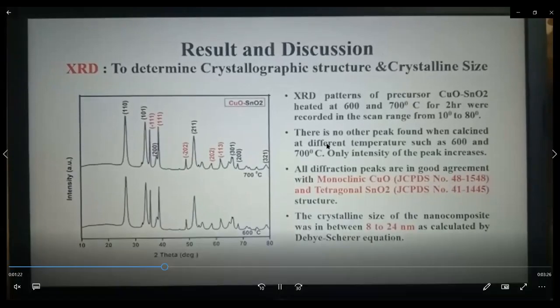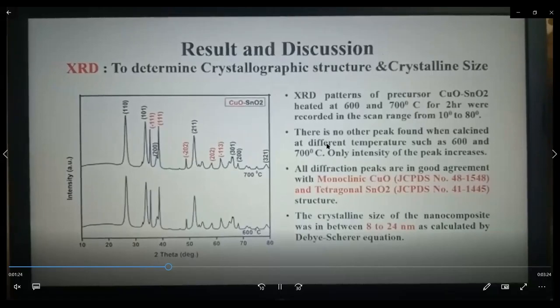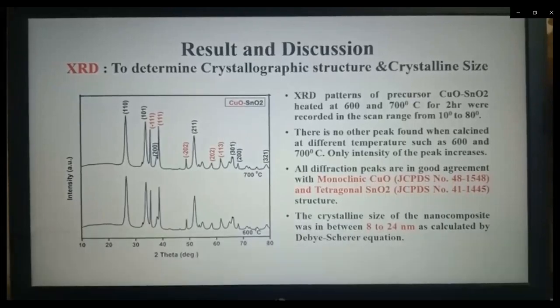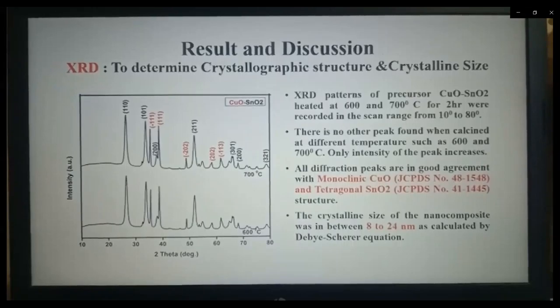XRD is used to determine the crystallographic structure and phase presence. So CuO is monoclinic, whereas SnO2 is tetragonal. And the crystalline size varies between 8 to 24 nanometer. How? Because CuO shows a crystalline size between 8 to 9, whereas SnO2 shows between 23 to 24. That's why we note the crystalline size of the nanocomposite was between 8 to 24 nanometer, by using Debye-Scherrer equation.